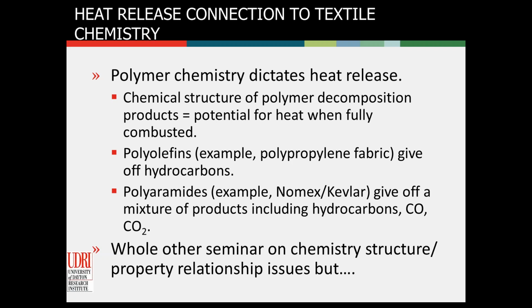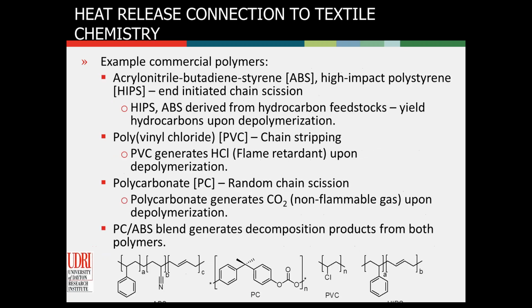So that chemical structure will dictate polymer decomposition products, and those decomposition products will have their own potential heat releases. Polyolefins are going to give off hydrocarbons. Not surprisingly, they're going to give off high levels of heat release. Polyaramides, Nomex, Kevlar, are going to give off a mixture of products, including hydrocarbons, carbon monoxide, CO2, and so on. So you have to look at those chemistries. I could give a whole other seminar on it, but just to demonstrate, here are some plastics. These are not fabrics, but I want to show you some of the chemical differences. You can't treat all these fabrics the same.